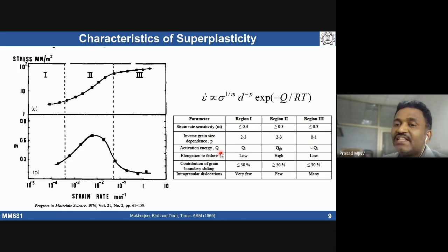And the activation energies, typically lattice diffusion activation energy for region 1, and grain boundary diffusion for region 2, in most of the cases. And region 3 will be close to lattice diffusion, or pipe diffusion can also happen. So elongation to failure will be maximum in region 2 because your m value is high. You can see higher elongation to failure.